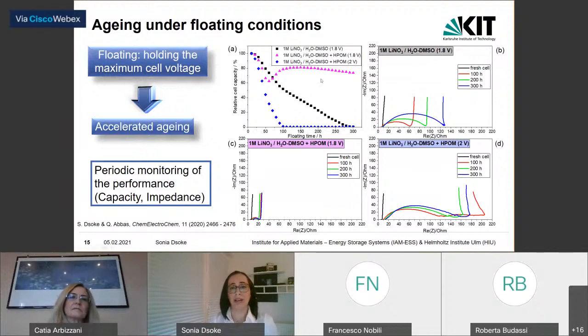So here there is the representation of the 3 different situations. We have in the black curve the system without polyoxometalate, kept at the floating potential of 1.8 volt. We performed this aging for a total of 300 hours, and every 10 hours we interrupted the experiment in order to monitor the performance in terms of capacity and impedance. And here you can see that the system without the polyoxometalate shows a decrease in performance with the floating time. And accordingly, we can observe an overall increase of the total impedance.